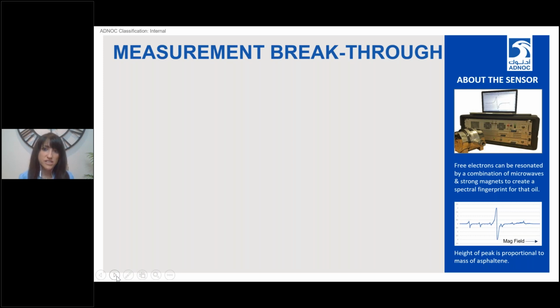It's based on the concept that asphaltenes have free radicals, and these radicals can resonate by applying strong magnetic fields. And so it has a unique signature, and we could measure the height of the peak, and that's proportional to the concentration of asphaltene in our fluid.